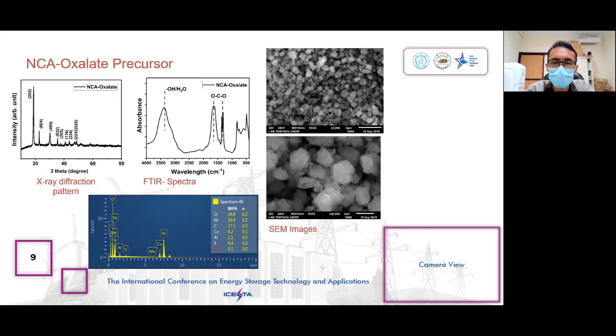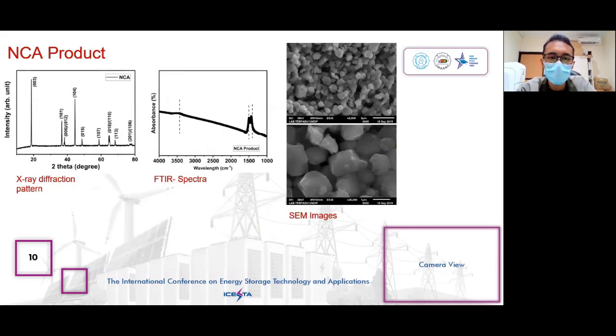The EDX analysis of NCA oxalate shows that the sample has high nickel content and small cobalt and aluminum content. X-ray diffractogram of as-prepared NCA, the peaks observed in this figure are indexed to the crystal phase. The FTIR spectra of NCA slightly show a peak at wave number around 3,400, which can be attributed to the presence of water molecules in the sample. This can be caused by water entrapment on the surface of the NCA particle due to humidity.